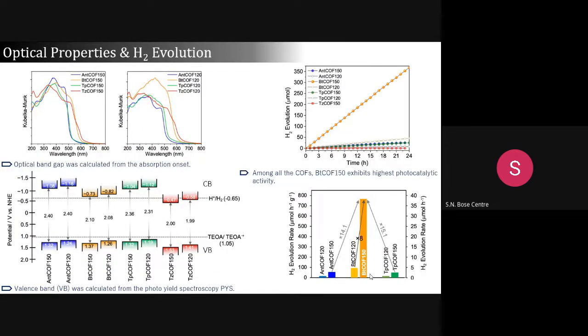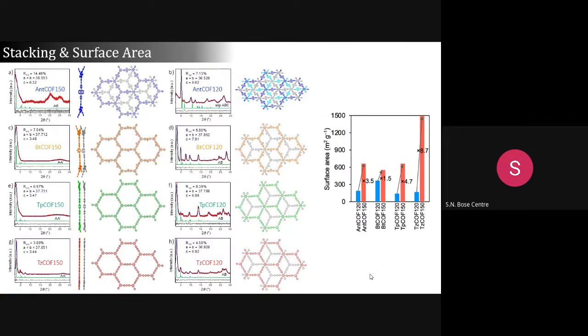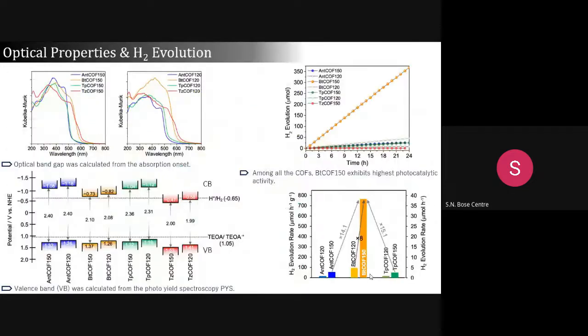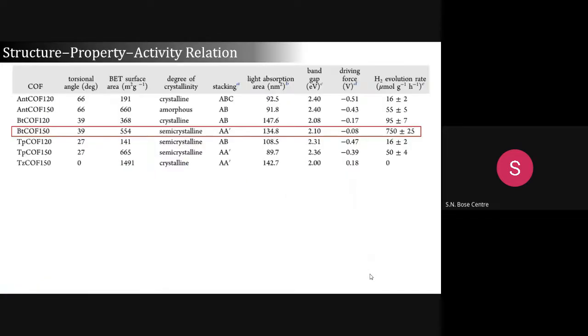Then we analyzed the hydrogen evolution, and we found this BT curve gives the maximum hydrogen evolution under visible light in comparison to the other curves. Although the BT curve does not have the highest porosity, it has similar porosity to the AMT curve or the TP curve, but the hydrogen evolution is so high, and theirs are quite low compared to it. We tried to investigate the reason. Is porosity the factor, or the packing, or something else? So we have analyzed all these things here.